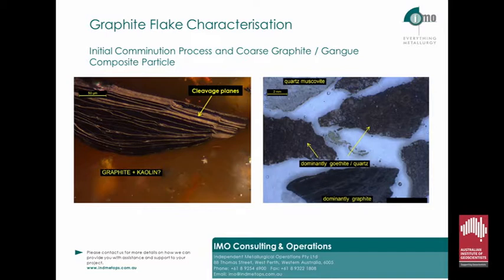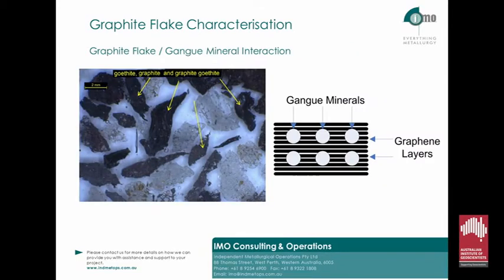The gangue mineral hardness has an effect on maintaining flake size. If the flake is surrounded by hard gangue minerals versus, for example, a clay, then more energy is required to liberate the gangue from the graphite, and it will be more difficult to maintain the flake content. The comminution techniques employed are, however, aimed to break the gangue and not the actual flake.